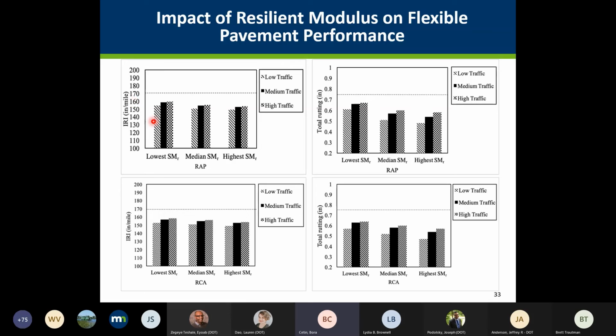The figure on the top left corner shows the impact of, of course, traffic load. With an increase in traffic load, of course, you see an increase in IRI across all graphs. So I won't touch base as much on the traffic load impact, since it wasn't really the main focus of the study. But how are the IRI values impacted by the SMR values? When we look at the figure here, of course, the RAP that has the lowest resilient modulus value had higher IRIs, and with an increase in the resilient modulus value, as expected, we see a slight decrease in the IRI value. And a similar trend was observed, even though it was less impacted, with the RCA materials, in the figure on the bottom left corner.